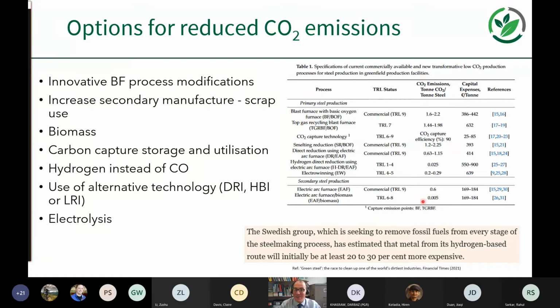With secondary steel, there's already significant opportunity to utilize those savings. So in the blast furnace, we're talking about innovative process modifications: top gas recycling, oxygen, high oxygen, etc. If we increase secondary manufacture from scrap use, then we've got associated emissions reductions with that. Also biomass, carbon capture, hydrogen instead of carbon monoxide as a reductant, and the use of alternative technology: direct reduced iron, hot briquetted iron, or low reduced iron as well. Or even electrolysis from molten iron oxide salts.